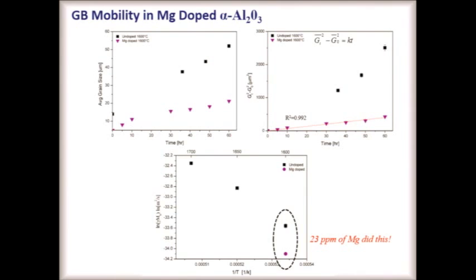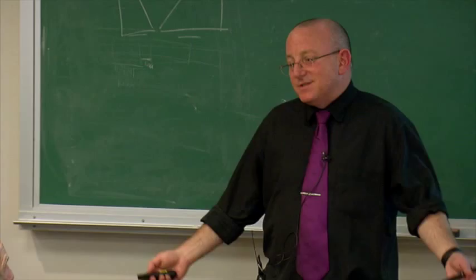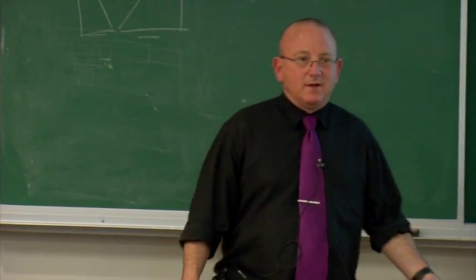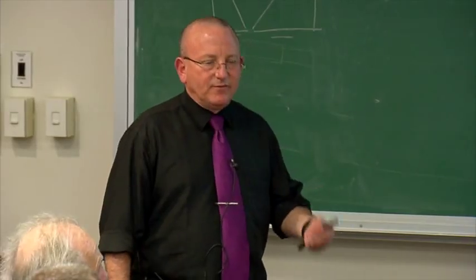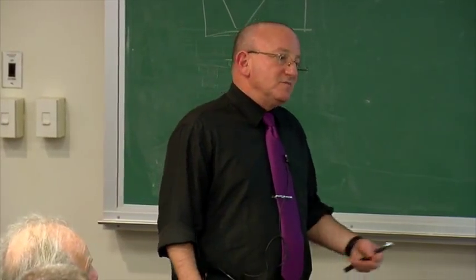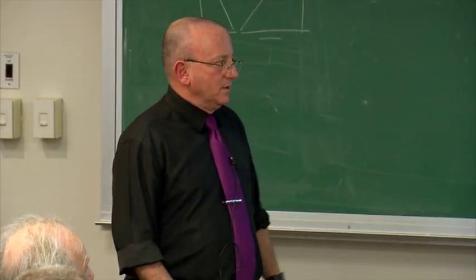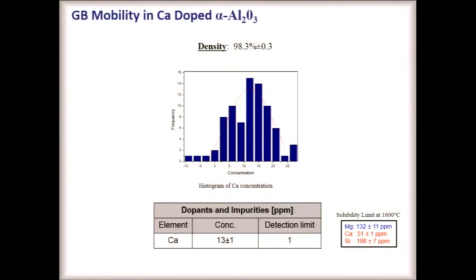So 23 ppm of magnesia does this to the grain boundary mobility. We all know that. That's what you see in the literature, what people who make alumina see. But now I can say that we're definitely below the solubility limit, and this must be this type of solute drag mechanism. What about calcium?